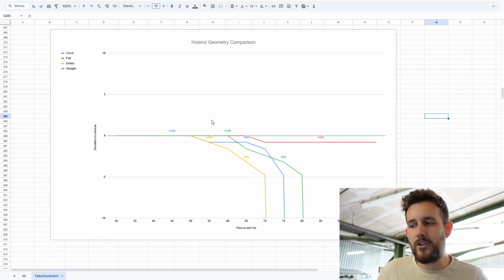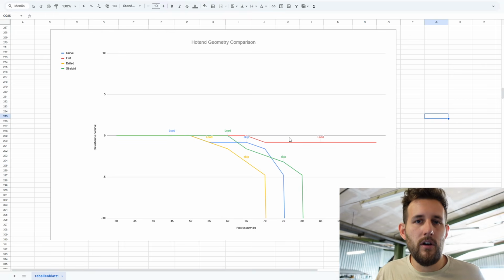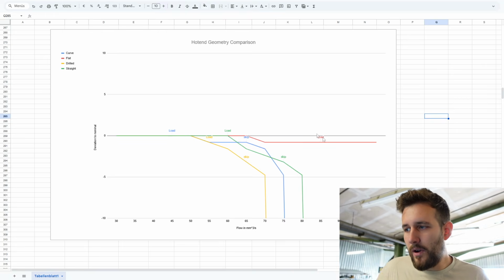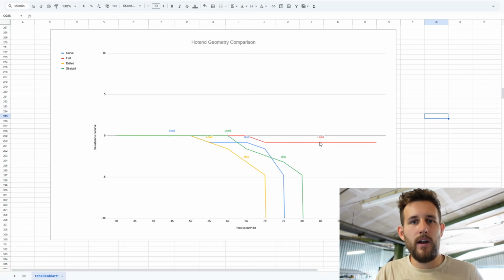But then have a look at the flat section, and this is what gets me really, really excited, is that basically up to a certain point, the deviation here from the zero line is basically 1%. It could be well within my measurement setup here on the precision scale, or just be the compressing of the filament or some sort of effect in that extrusion. But the point that I specified as the load point is actually way past everything else, where every other hot end was already skipping. I could see those changes in die swell, in extrusion width, in viscosity of the extruded material. And basically even at 100 cubes it still kept going.